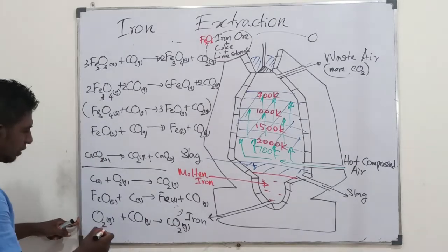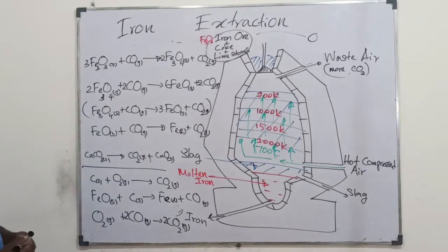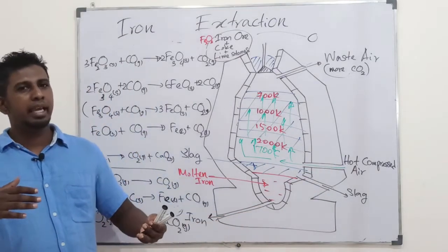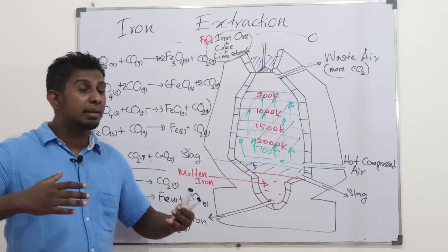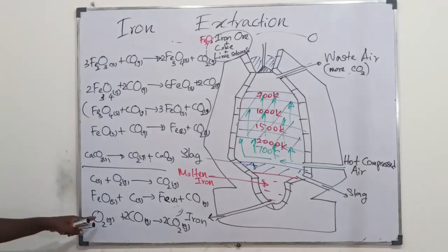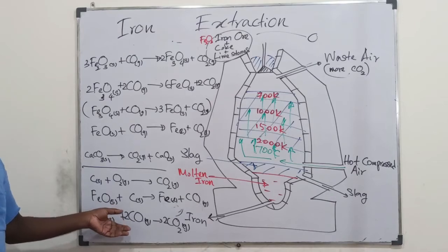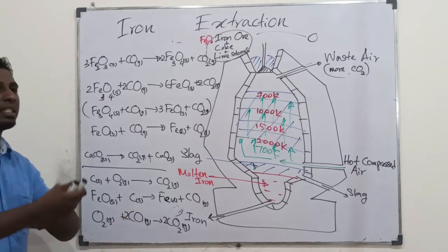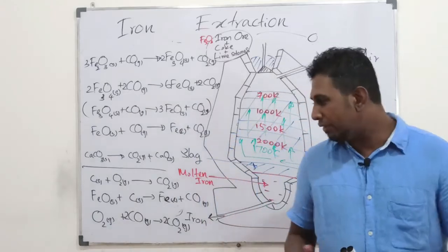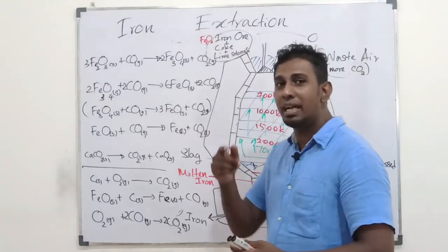So it's quite disadvantageous, and if you provide more air, meaning if the rate of air supply is greater than what is required, we could have this reaction also at the bottom. So it reduces the amount of carbon monoxide, which provides our driving force for the reaction. Therefore, we need to avoid having this reaction. Therefore, we need to make sure of that. Now you get the point.